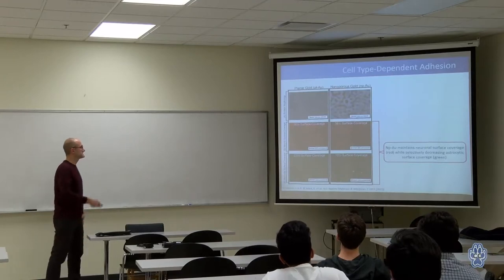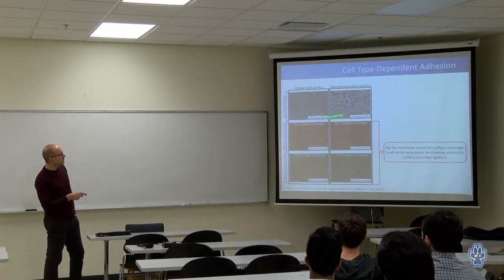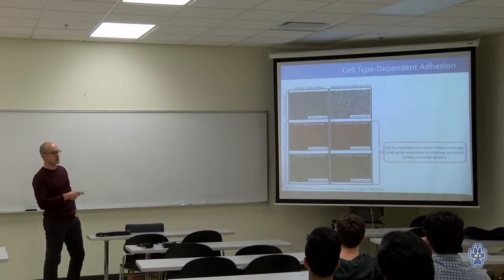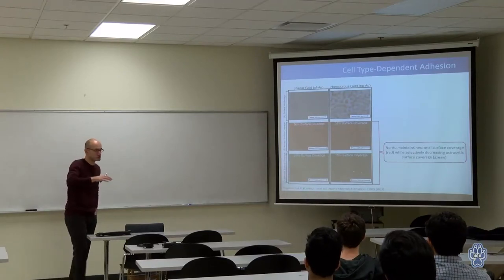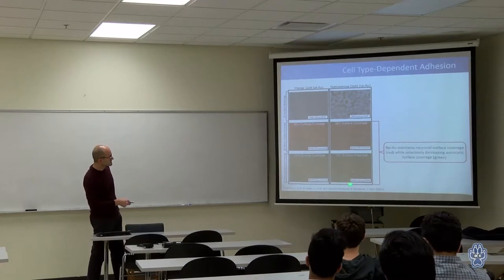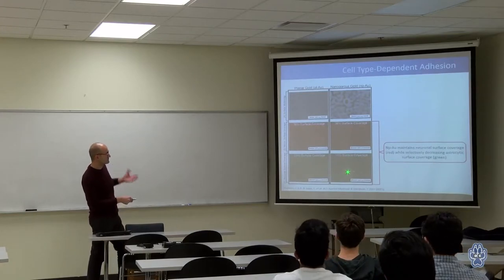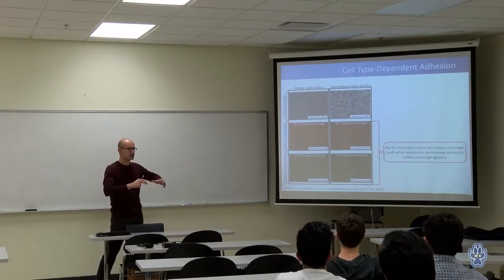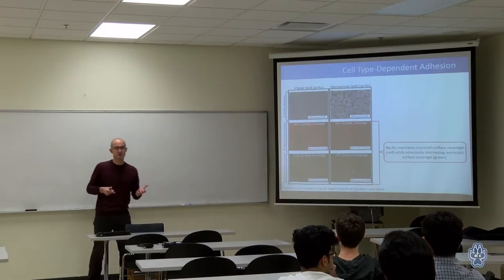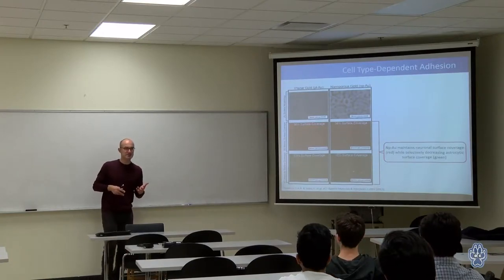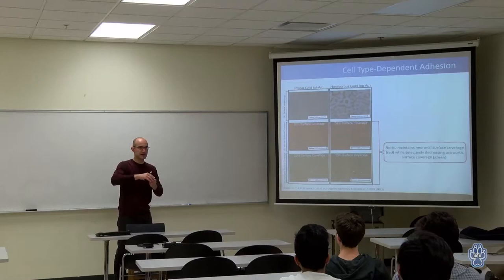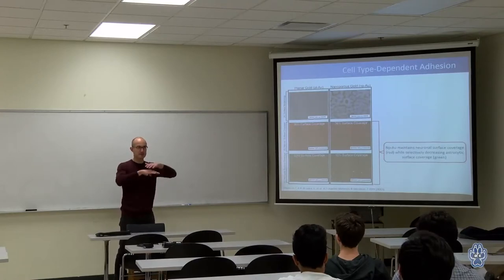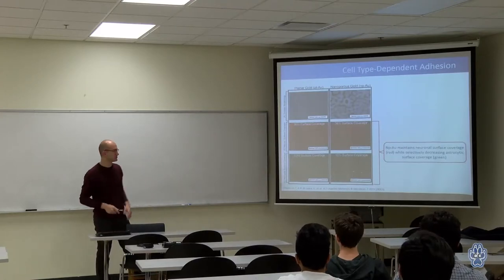So what we've seen is, these are a little bit hard to see, but the neurons were not actually affected by the surfaces, whether it's on gold or nanoporous gold, which is nice, because we want the neurons to be close to the surface. But those scar-forming cells actually got reduced, or they were less spread on the porous gold, which is also nice, because this suggests that the neurons can stick better and astrocytes, the cells that we don't want to enter between the neuron and the electrode, are kind of deterred.